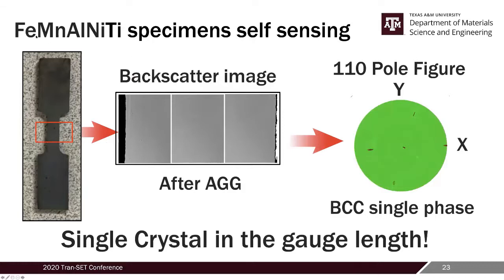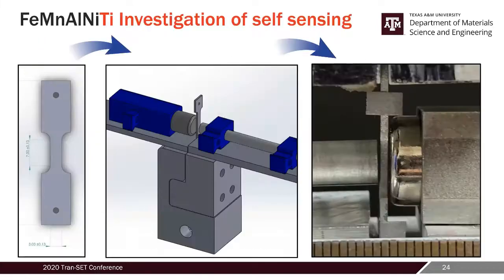And again, we tested iron manganese nickel titanium specimens. After abnormal grain growth, we didn't observe any grain boundaries. That means that we have single crystals, because we measured the gauge length in XRD. And we tested our sample. Here is how our sample looks. We designed this in SolidWorks, and this is our setup. And we measured the magnetic change during the superelastic